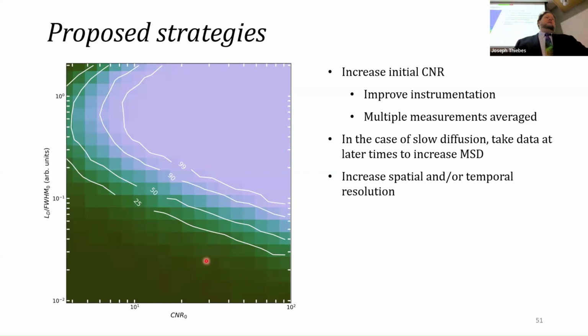It can help a lot if you're doubling your spatial or temporal resolution, but you have to get pretty high before trying to get off of this rail down here is pretty hard because, as you can see, this is a logarithmic scale on the contrast to noise. And so, you get out to 1,000, this line is linear in this scale. It doesn't come down that far. So that may or may not help in your situation.